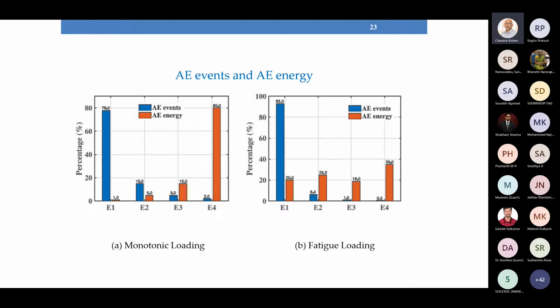Whereas in the case of fatigue loading, almost all different energy contributions are there. And the number of events, you can see that the E1 corresponds to the large number of events, almost 90% of the events compared to the energy level 4. That means only microcracks are formed for almost 90% of the life, and later on, just before failure, they coalesce and form a macro crack. So it's more like a brittle kind of failure, a sudden failure which occurs under fatigue loading.